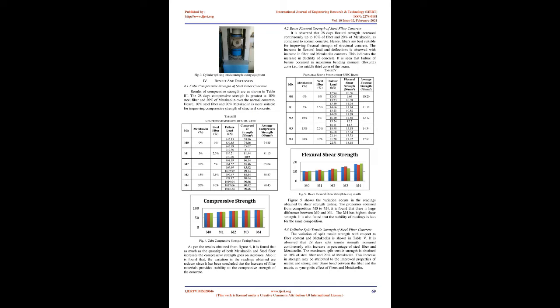Fine aggregate. Good quality graded sand was selected, and fineness modulus should be controlled in 2.3 to 3.0. Fine aggregate performance was checked according to GB 14684-2011. Coarse aggregate. Test selection of hard texture, graded continuous gravel, and aggregate shape with a more uniform edge polyhedron was made as well, with a particle size of 5 mm to 20 mm and clay content.